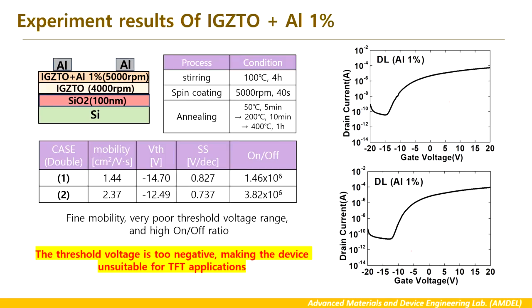Finally, we tested IGZTO doped with 1% aluminum. The results showed fine mobility and a high on-off ratio. However, the threshold voltage shifted too negatively, which is a serious drawback. Because of this issue, the device is unsuitable for practical TFT applications.